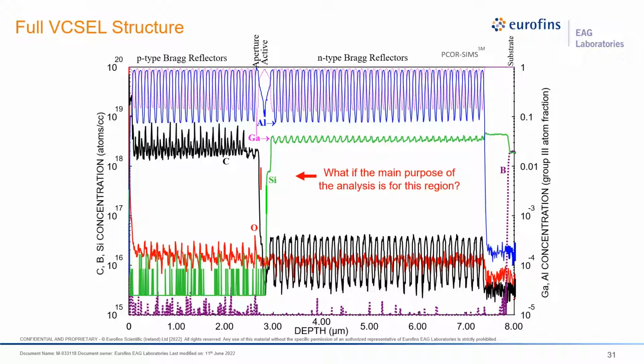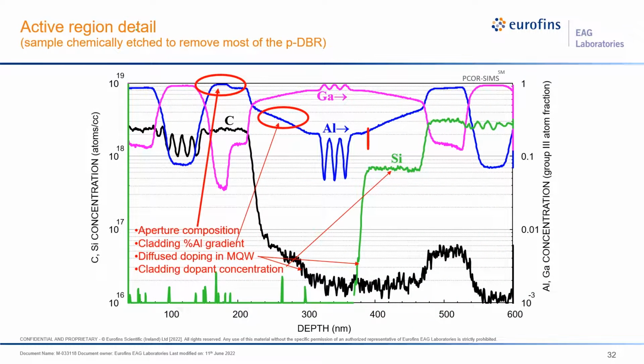But PCOR-SIMS can also provide insights into the structure of the active region, which is circled here in red. PCOR-SIMS can reveal the aluminum profile, which varies on both sides of the active layer. There is a grading from the P-type aperture layer and also from the N-type DBR to the cladding layers, where it is followed by a steep drop in aluminum content, which is lower in the barrier layers immediately surrounding the aluminum gallium arsenide active layer. The detailed picture of the active region is also helpful in assessing whether the lasing mode in the optical cavity is in the optimal position.